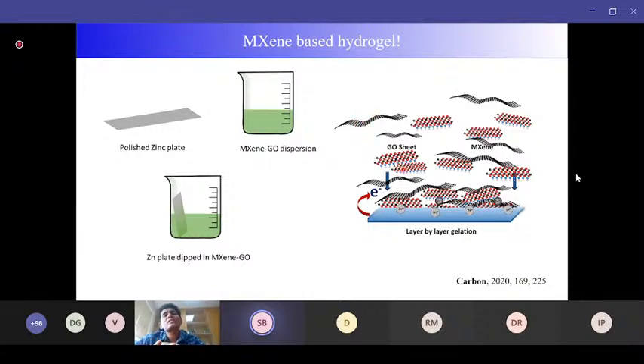So this ceramic structure has less sheet to sheet interaction, and the sheets of the MXenes are much smaller also, because graphene sheets are like 10 micron, whereas the MXene sheets are like 1 micron. So they have less interaction. That's why we cannot make the freestanding MXene hydrogel. So we tried to introduce a little bit of graphene over there, like 5% to 20%. The lowest one was 5%. So with 5% graphene, can we get a freestanding structure made of the MXene and the graphene, where the MXene is 95%? We still call this an MXene hydrogel, but the role of graphene is the gelator.